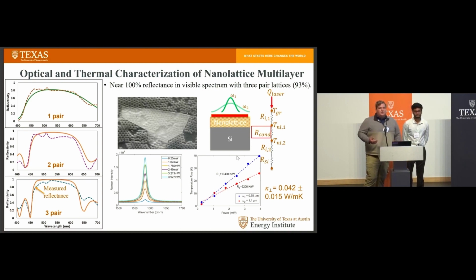In our current model, we model it as 1D, and because it should be an ultra-low thermal conductivity nanolattice, that conductive thermal resistance will dominate the circuit. So we can extract an effective thermal conductivity, which at the moment we are measuring 0.042 watts per meter Kelvin, which is still pretty low, but there is more thermal characterization to work, and we're happy to talk to you guys at the poster presentation above.